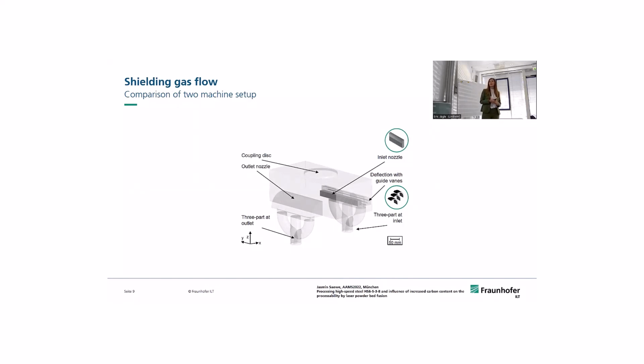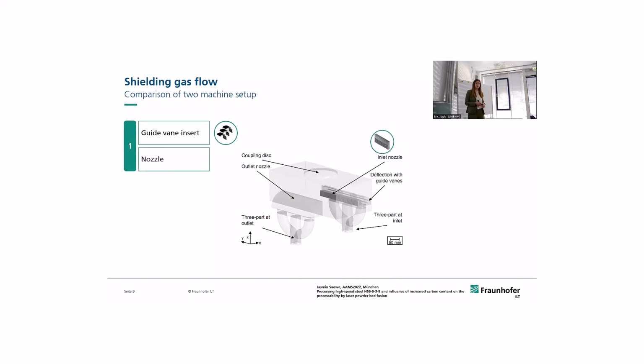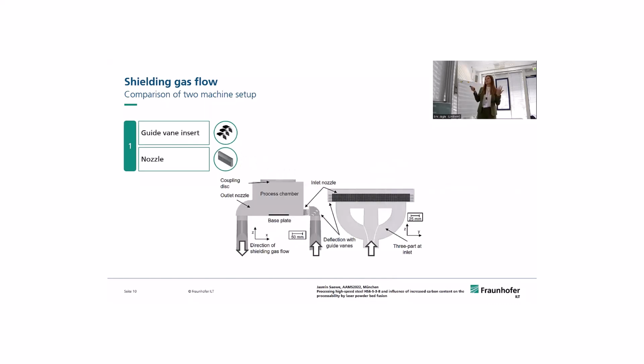This is the setup of the Econity machine that we used. It's actually as delivered, except for those guide vanes that we integrated ourselves, because here we have a three-part gas flow insert, and then the inlet nozzle, and to help the shielding gas flow move around 90 degrees, we integrated those guide vanes, thinking that it might be beneficial. That is the first shielding gas flow setup that I used, with the guide vane inserts and the inlet nozzle. You can see it from different perspectives.